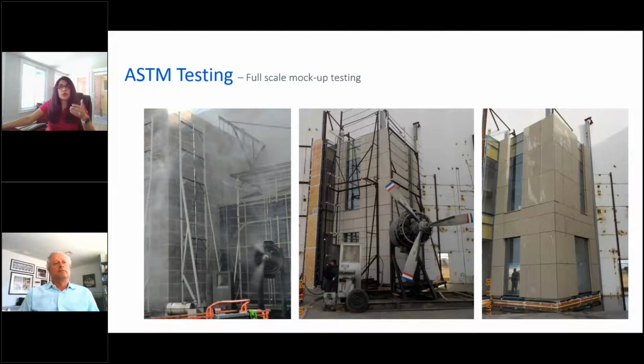It performed extremely well. The whole system moved in racking, and up to 3 inches, we hardly saw any cracking in the stone or any joints getting too close to each other. We actually tested it to 4.5 inches with very little failure, just joints closing in the end. And again, this proves that once you do the testing and once you actually use proper safety factors, the cracking and breaking of the stone can be avoided significantly. Yeah, it was very interesting, and we were actually pleasantly surprised at how resilient the system was with that much racking in it.